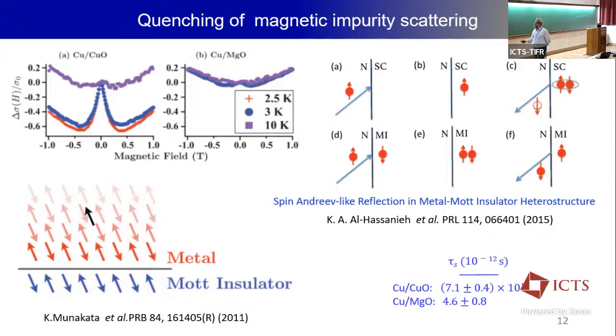Now look at the magnetoconductance data. They see a very clear signature of a weak anti-localization effect when copper is grown on copper oxide. But when you grow copper on MgO, a band insulator, this feature goes away. They modeled this based on the formalism of weak anti-localization, and they found that the spin flip scattering time is anomalously large when the copper is grown on an antiferromagnetic insulator as compared to when it is grown on a band insulator. And this number is really large.